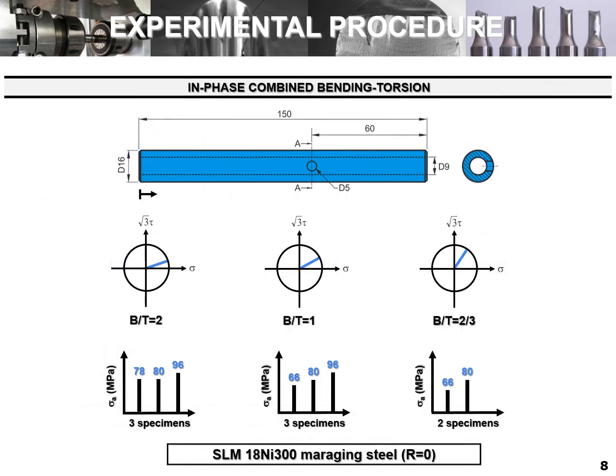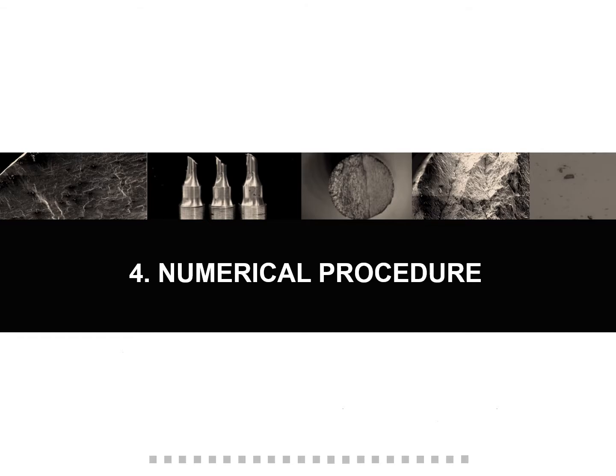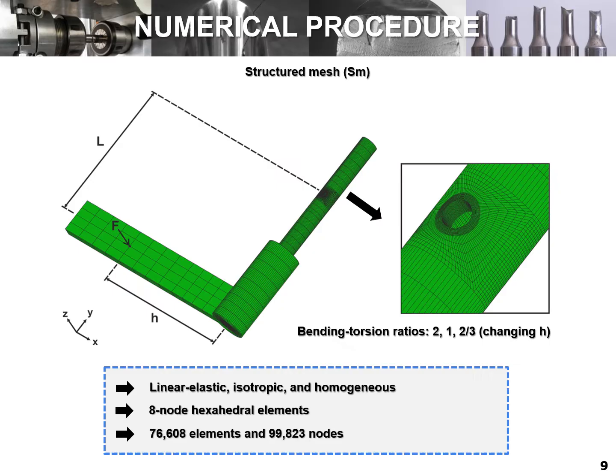As far as the multiaxial fatigue tests are concerned, the geometry selected was a hollow cylindrical specimen with a transverse hole. The tests were conducted under pulsating loading conditions for 3 different ratios of bending moment to torsion moment. The crack detection was done in situ by means of a high-resolution digital camera.